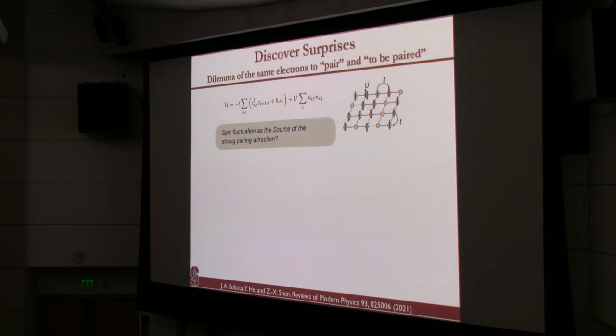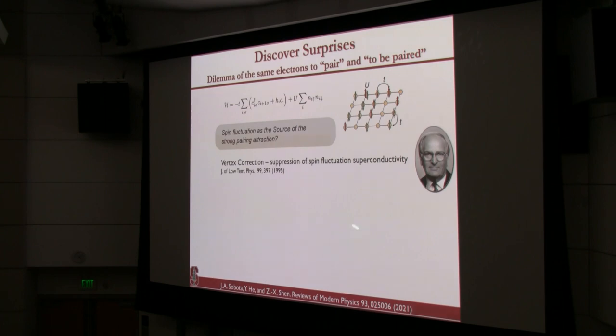Unlike a phonon problem, where you have electrons and phonons as different things, the electrons get a retarded attractive interaction from the phonons, and you don't need to worry about the phonon. In a one-band electron system, those electrons have to play two roles, to pair and to be paired. In other words, they have to be the athletes and the referees at the same time. This is a very challenging theoretical problem. Okay? So the warning was given fairly early on by Bob Schrieffer.